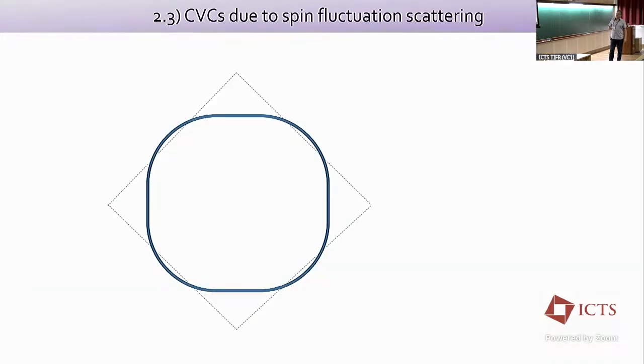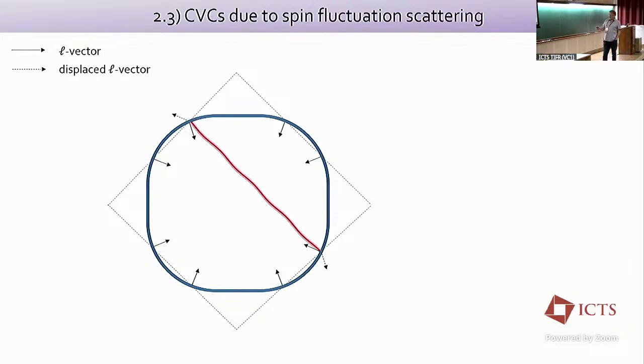So here's our Fermi surface. We draw on it the antiferromagnetic zone boundary, and then you can take the mean free path vectors, or if you like, the velocity vectors at these points, and then with the vertex corrections, as Kontani showed, when you scatter strongly between these points, you can essentially add these two. So the effective velocity, or the current, is no longer perpendicular to the Fermi surface, but in fact now has a new direction.